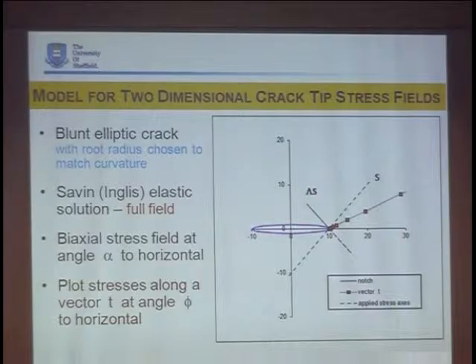A singular crack can only be found in the mind of a mathematician. In real life, if a crack exists, it's got to be at least 2 or 3 atomic dimensions wide at the crack tip. Otherwise, if you get to 1 atomic dimension wide, you've really just got a dislocation. Less than that, the crack isn't there at all. So there must be at least a finite radius of curvature here.